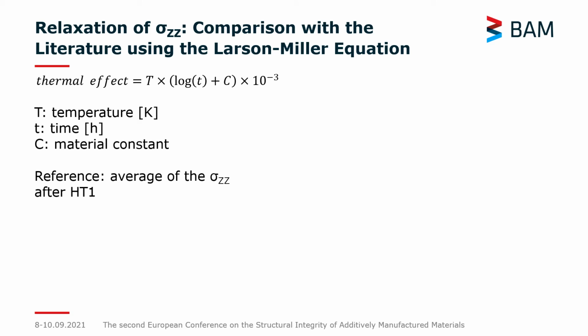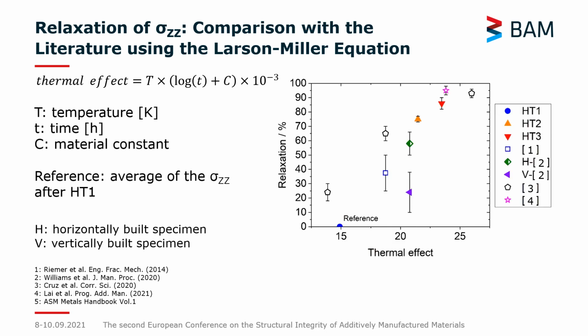Now we would like to compare our relaxation results with other findings in the literature, and we can do this by using the Larson-Miller equation. So we want to plot the relaxation versus the thermal effect, which takes into account the temperature in Kelvin, the time in hours, as well as a material constant for stainless steels, which is between 20 and 22. For the plot that will follow, we use the stresses in the build direction after the first heat treatment. And what we see is that our results, so 900 degrees and 800 degrees applied for 1 hour, fit a nice trend which ends in a plateau once we reach a thermal effect of about 24, which corresponds to a relaxation between 85 and 90%.